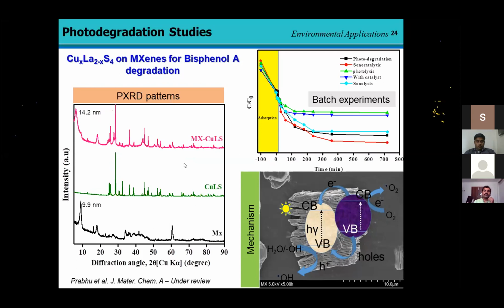Then we found good results using sonocatalytic degradation. Sonocatalytic degradation is nothing but sonication along with visible light. Then we also checked photodegradation, sonocatalytic degradation, photolysis with photocatalyst, and sonolysis. Among them, sonocatalytic degradation had much higher efficiency than the other methods developed here. We are also looking for better results on the mechanism part, and the results we got were quite impressive.